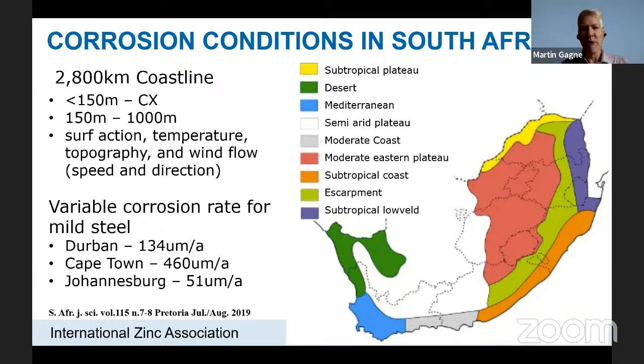They measured the corrosion rate in all of these environments by putting out mild steel panels and measuring the corrosion rate of mild steel. On the subtropical coast in the east near Durban, they were measuring 134 microns per year. However, in Cape Town, in the Mediterranean zone, 460 microns per year, so much more corrosive. And while there is more rainfall in Durban, there's much more surf action in Cape Town. It's this dispersion of chlorides in the air that is more important for the corrosivity in this area compared to Durban.